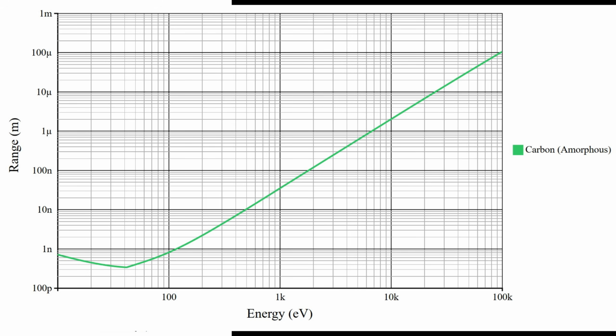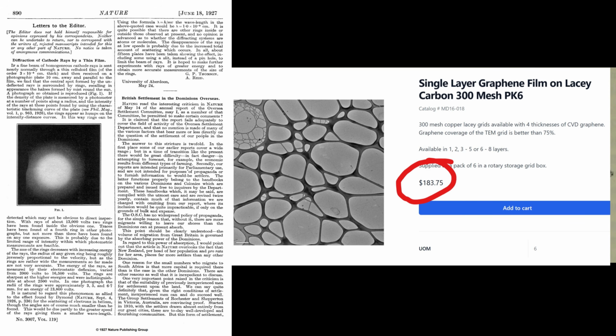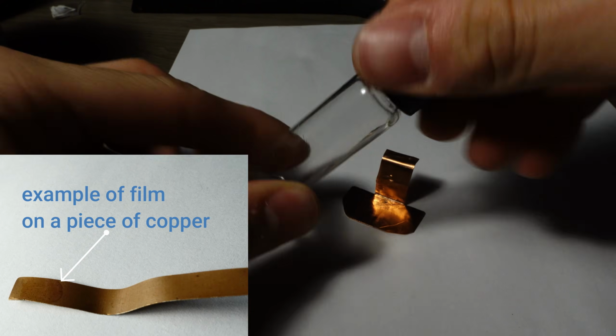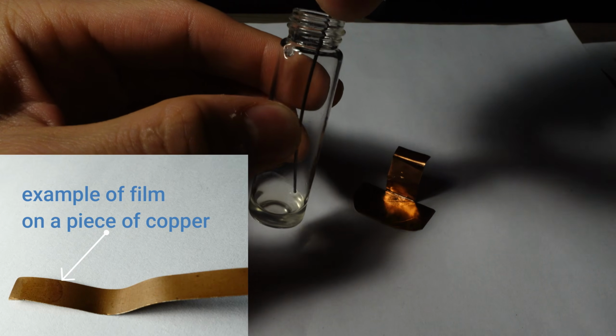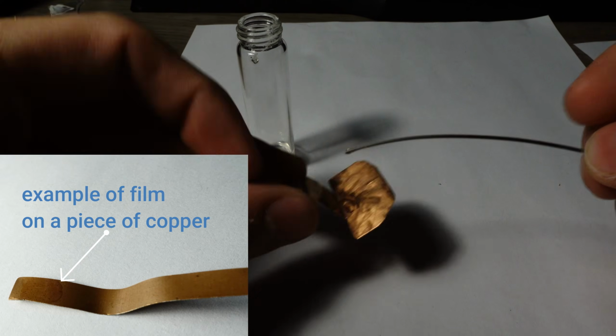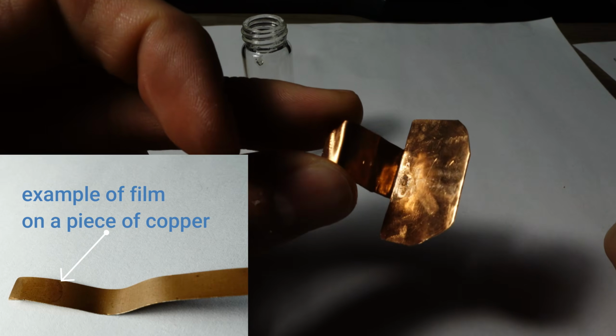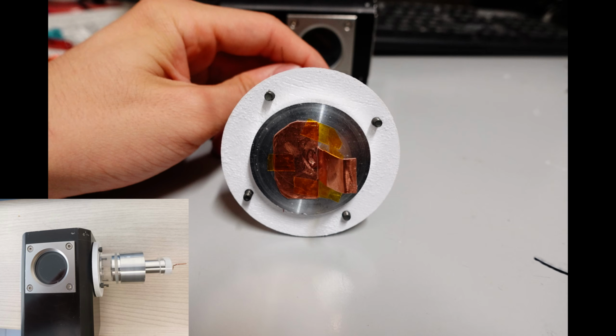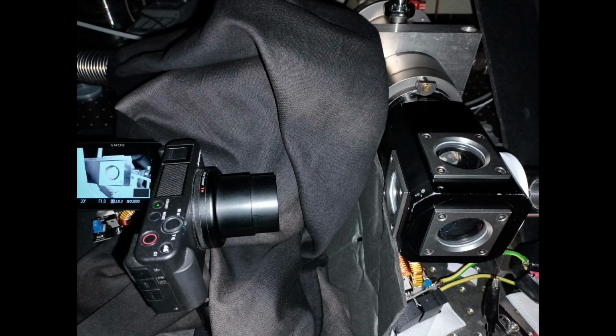I could get a graphene single layer, but they are very expensive. So I decided to try and use a nitrocellulose layer, made simply by placing a drop of the dissolved cellulose on the whole aperture and letting it dry. This should yield us a very thin layer, a few molecules thick, that electrons can penetrate. I then placed the pinhole with the celluloid on the electron trajectory and looked at the transmitted beam. This required quite a long exposure, as the intensity of the diffracted electrons is very low.